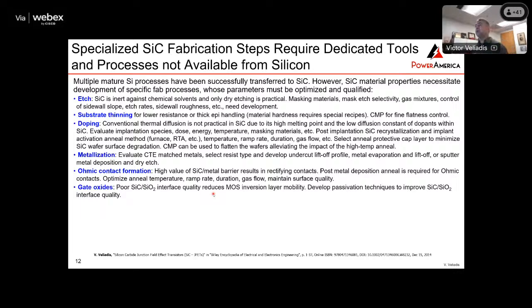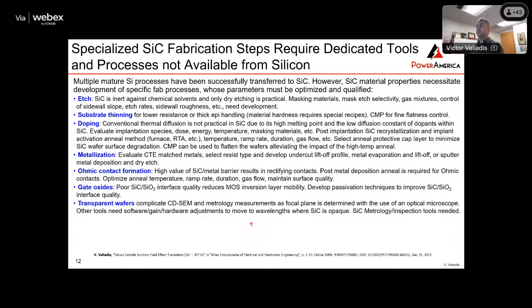The gate oxide, if you're making a MOSFET, then there's an oxide that's interfacing with the silicon carbide, and the interface of the oxide with the silicon carbide, unfortunately, is very poor in terms of roughness and in terms of defects. There are a lot of traps, a lot of defects in that interface, and those compromise your mobility in silicon carbide. So you got to improve the quality of the silicon carbide gate oxide interface. The wafers of silicon carbide, because of its wide band gap, as expected, they're transparent. Silicon wafers, because of the lower band gap, they're opaque. So you need equipment that uses laser beams or optical light that's meant for transparent wafers.